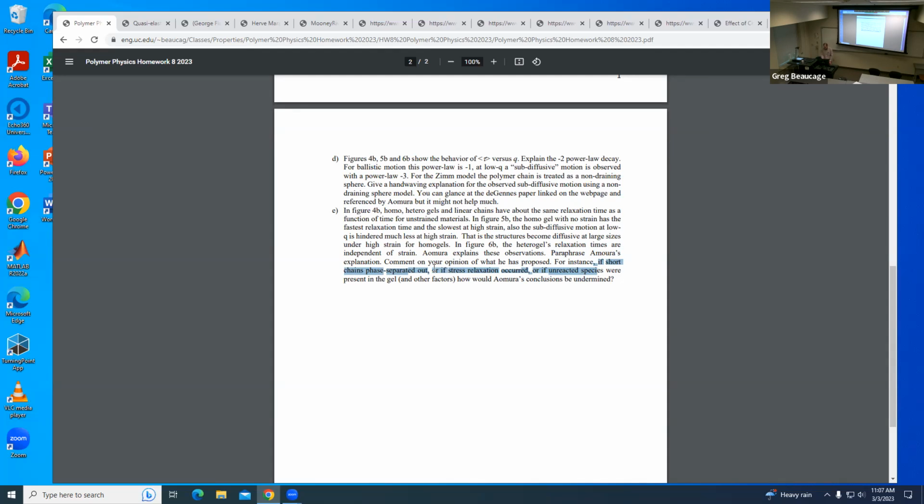So the last question I'm trying to ask you is to reject this paper, like say how he messed up, even just from an experimental point of view. If you pull on Jello and hold it, it's going to relax. It isn't going to stay stretched, so he hasn't even considered that. All we'd have to do is do that in an Instron and watch the stress decay and see how much time he had. He didn't bother to do that. You can do that in any lab, right? Or you can just put a weight on and watch how the length changes with time. That's also kind of stress relaxation, so you wouldn't even need an Instron.